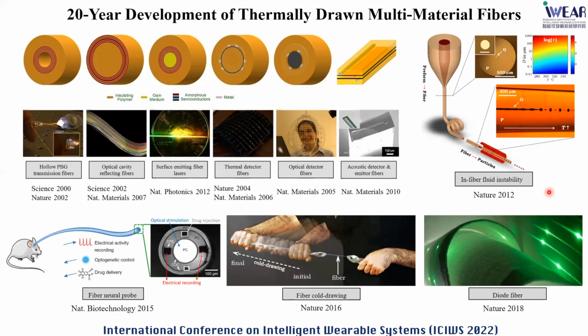If we look at the fabrication technology here, we need to assemble all the solid materials in the preform, and thermally stretch that into the thin fiber. So all the materials that we encapsulate inside the preform will go through different phase transitions, for example, from the solid to the liquid, and further to the solid phase. And those phase transitions further limit the material selection.